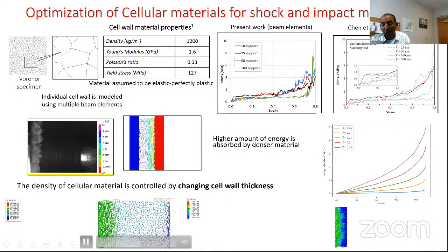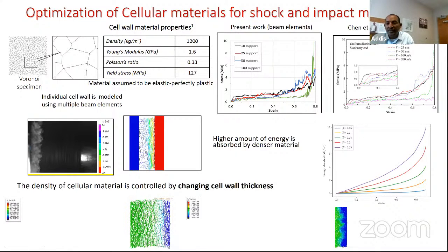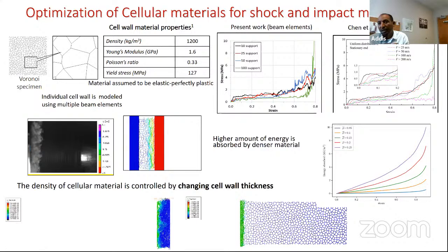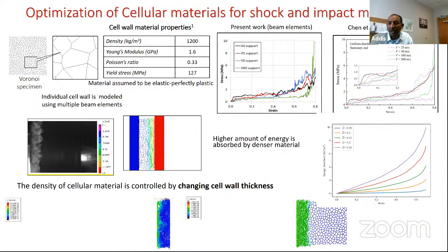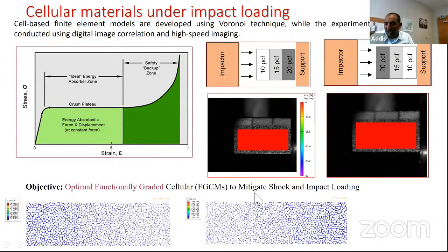You can see that the right side has also started deforming. When you increase the velocity of the impact, you would see that there will be a response from the right side that interacts with the stress propagation from the left side, which changes the way the material responds. On the other hand, if you hit the specimen on the softer side, you will see only one type of deformation. So by changing the way these are arranged, we hope to find a better configuration to absorb more energy. Experimentally, we used 3-layer systems where we have cellular materials with different densities. They are attached together, as shown here.